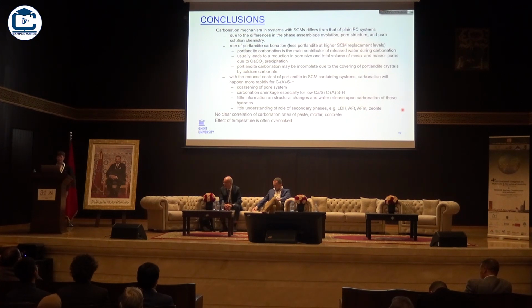Carbonation of Portlandite leads to a reduction in porosity, but Portlandite carbonation may in reality be incomplete because of covering of the Portlandite crystals with calcium carbonate. With reduced content of Portlandite in SCM-containing systems, carbonation will go more rapidly, certainly if you have CASH instead of pure CSH, which will lead to a coarsening of the pore structure, maybe some carbonation shrinkage, but there is still room for further research because some of these aspects are not fully understood yet. For instance, what is the role of the secondary phases that might have a positive effect against carbonation, like layered double hydroxides and so on.